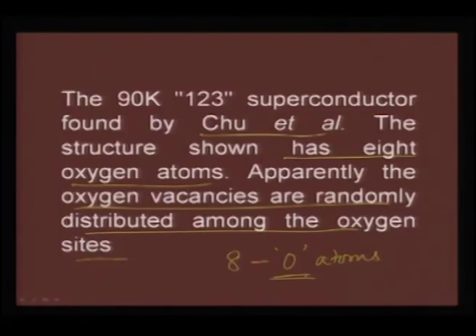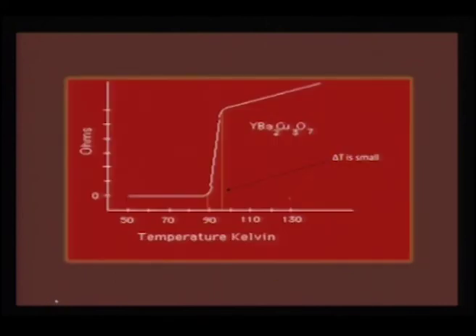In the next few slides, when we discuss the chemistry of it, I will show you how vulnerable these oxygen atoms could be, and if we are not very careful in maintaining these oxygens in the preferred lattice sites, you will end up with an insulating compound which is not even going to be metallic. So, that is the chemistry which is rich in this lattice cell, and then we will look at it.